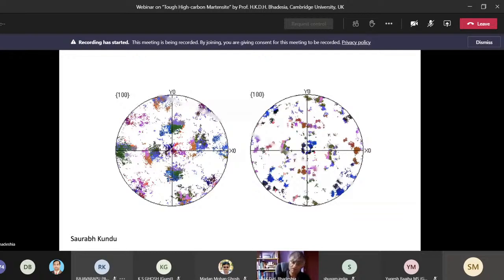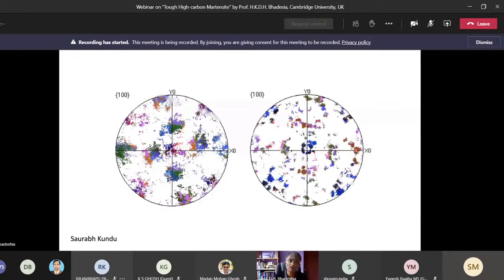Sorry, this is in the wrong order. This is the undeformed material, and the austenite grain is undeformed. And you see very little spread in orientations from the expected orientations. When we transform to martensite from deformed austenite, there's a huge variation in the orientations, and that's because this pancaked grain has been divided up into regions which are very small in terms of coherent domains, and the martensite plates cannot cross those domains, and also those domains within a single austenite grain have misorientations. So instead of generating just 24 different orientations, we have thousands of different orientations of martensite plates in one austenite grain.